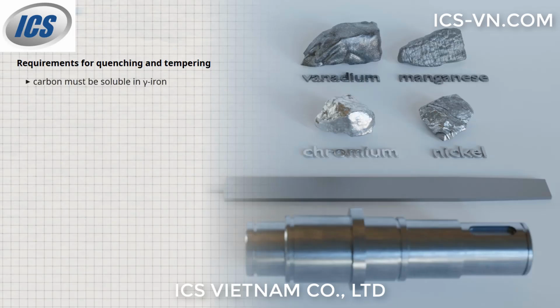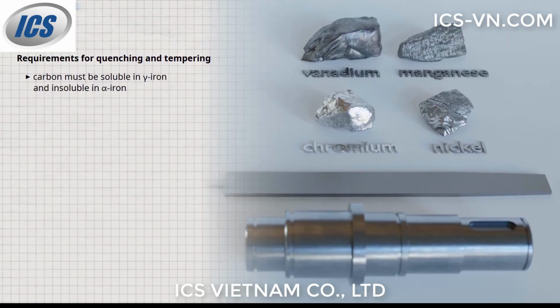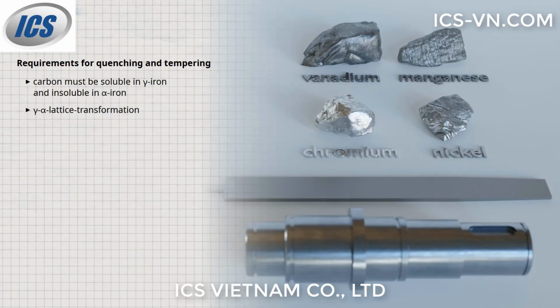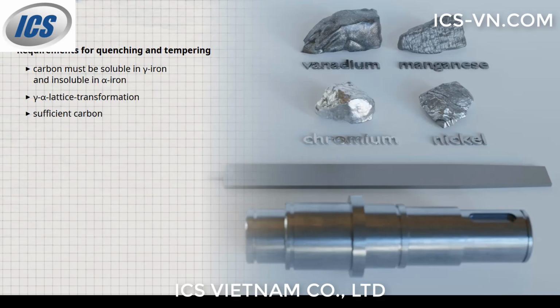First, carbon must be soluble in gamma iron and insoluble in alpha iron. Second, the gamma-alpha transformation must be present and not suppressed by alloying elements. Thirdly, there must be sufficient carbon to give a significant increase in hardness or strength and to make hardening and tempering economical.